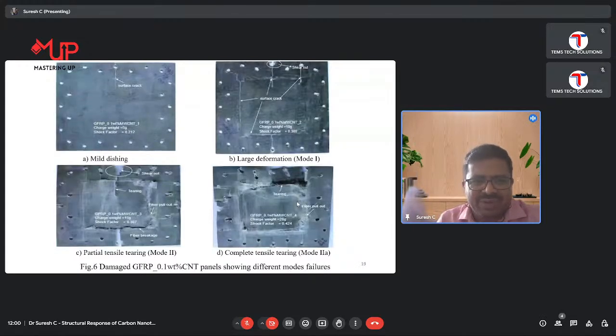Next, when we see the 0.1 weight percentage of composites, there was a slight crack at 5 grams in one of the bolted edges. And for 10 grams, we can see there was a shear out in one of the bolt edges, and there was a slight crack in all the edges. But the amount of deformation has reduced when CNT is increased. When we go for 15 grams, the damage was much more severe.